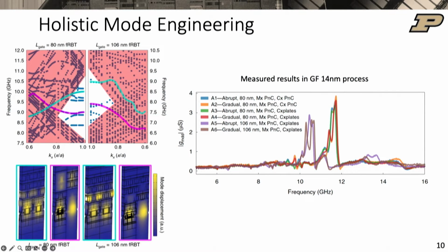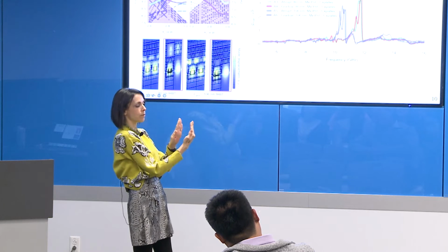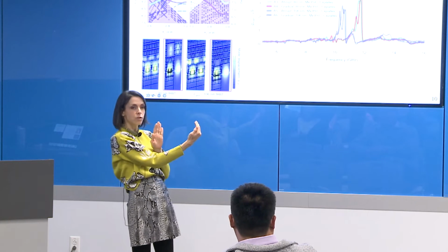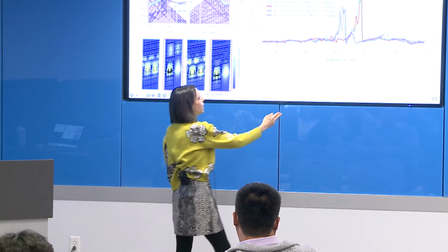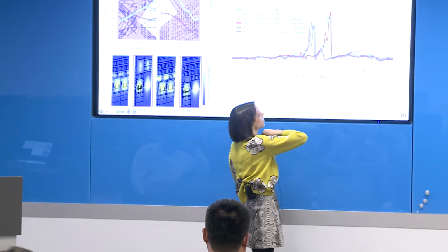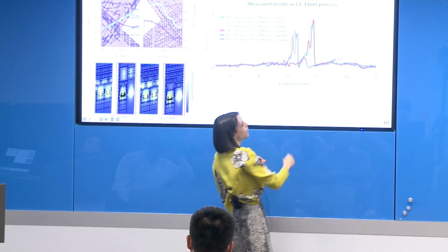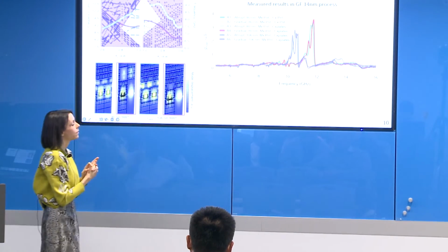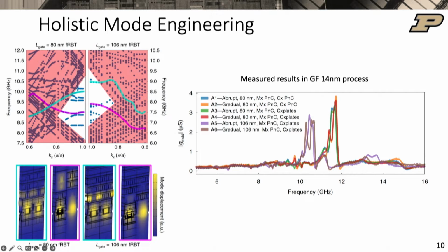So we looked at various different examples of how to make that lateral transition, gradual and abrupt transitions under different gate lengths. So the gate length, as I mentioned, we're vibrating in this dimension. So if we have a longer gate, then we actually have a lower frequency. And you can see a cluster of devices with lower frequency here, cluster of devices with higher frequency corresponding to these different gate lengths.